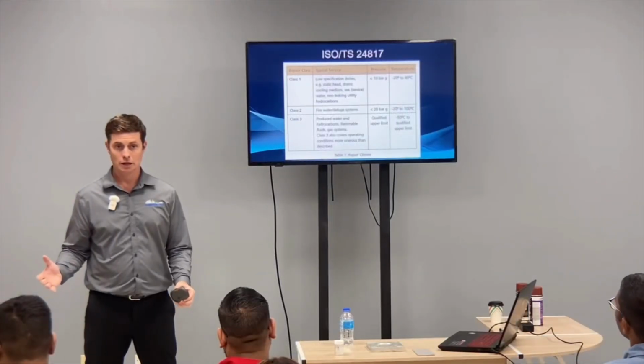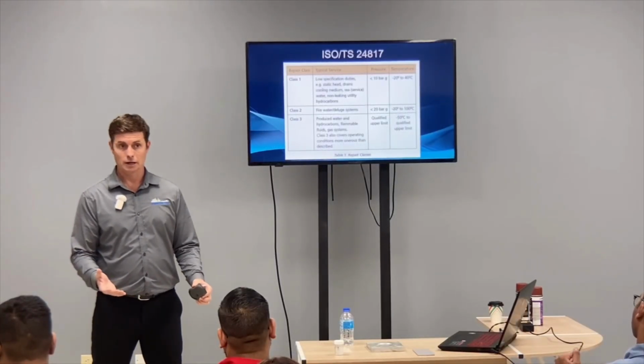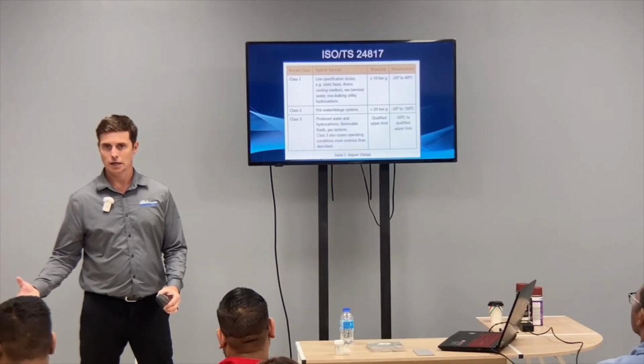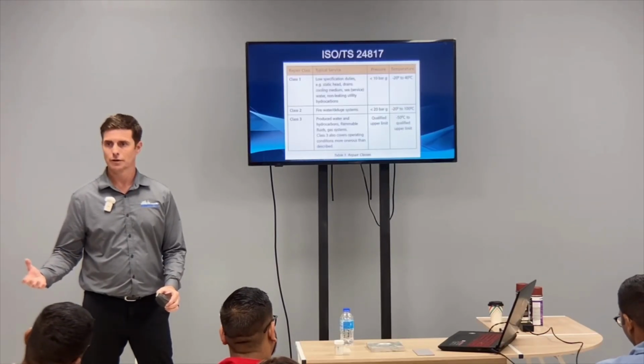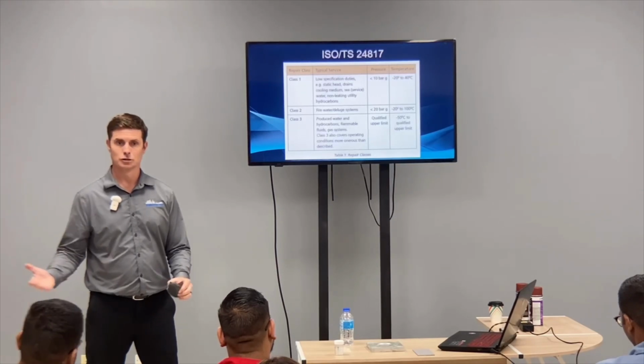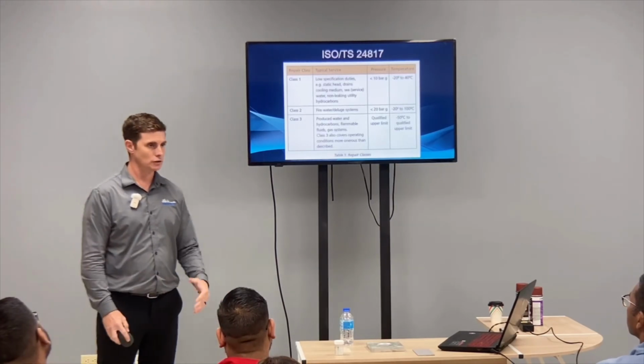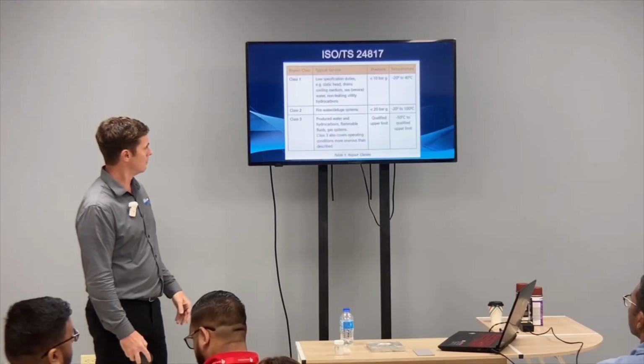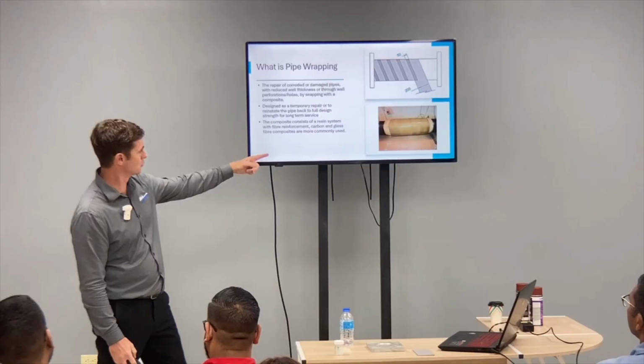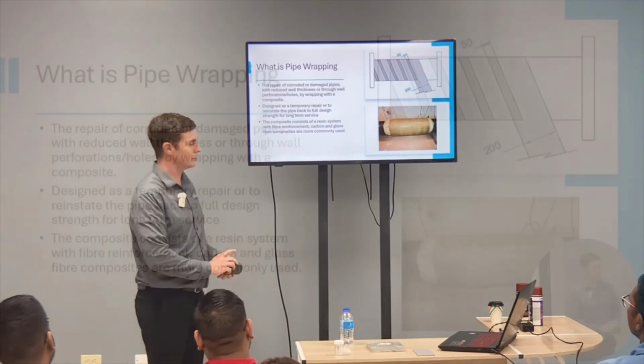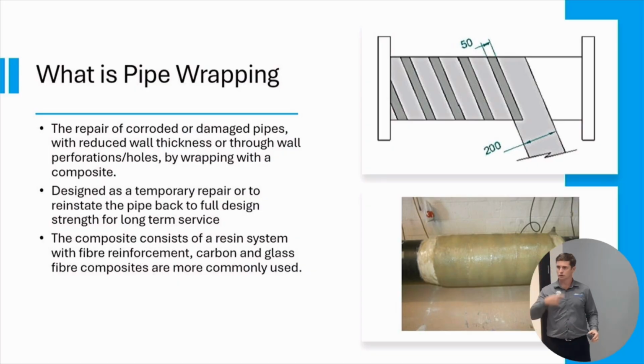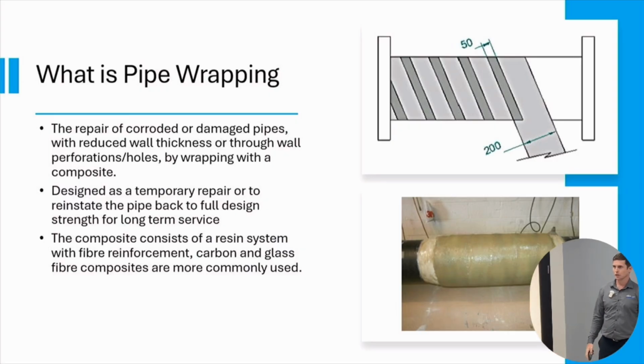This is something that Qualitech can spec, and then they can also stock, and then it's just a matter of having relationships with engineers to have a turnaround very quick. So just keep us in mind whenever you do have problems on your pipes and you need to do pipe wrapping. It can really, really get you out of a jam. Here's a picture of some pipe wrapping in the lab. The designs vary depending on the situation. But you have multiple layers of laminate, then you sandwich it with coating, so on and so forth. It ends up looking like a Big Mac that you wouldn't want to eat, but it'll work really well whenever you're looking at reducing corrosion.